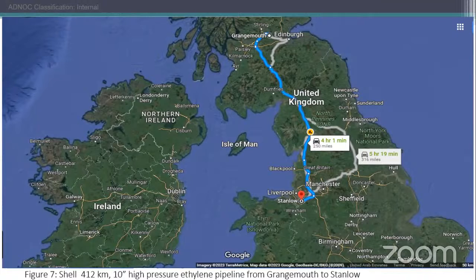When this inspection was done, they realized that there were some points where they had this pitting, these indications. But in their mind, they probably felt that this may have been due to microbial action, or other forms of corrosion. So they did their part as corrosion and inspection require: they reinforced the section, they sleeved that section to increase the wall thickness. Then in 1999, they repeated the same inspection. They discovered that this same pitting was also present, in the same area with the same indication.